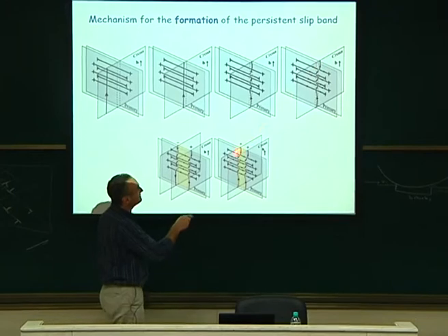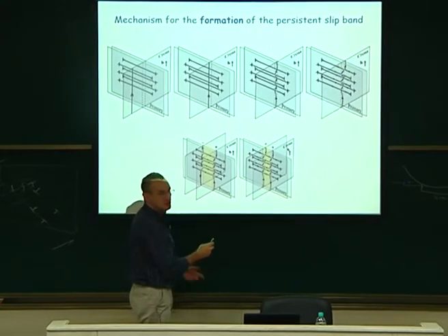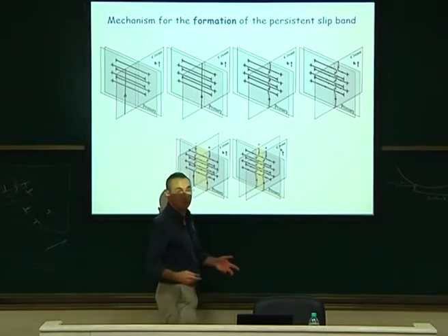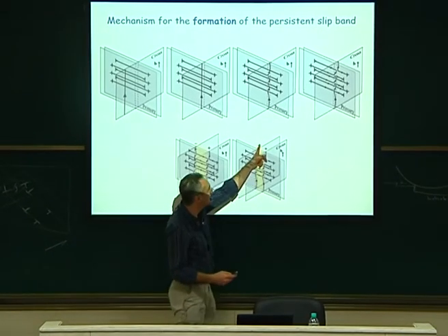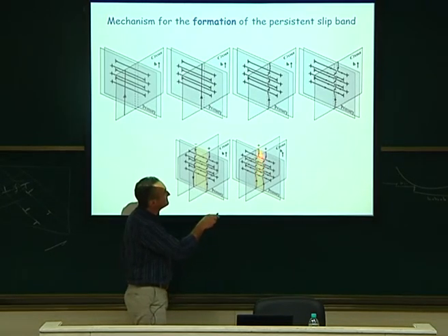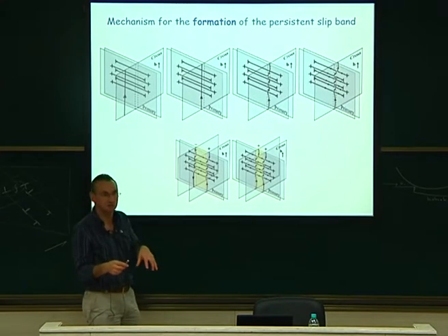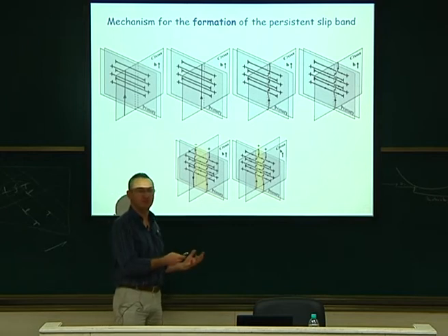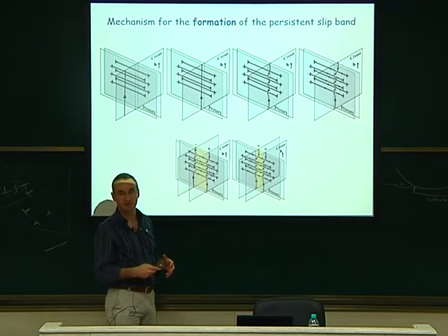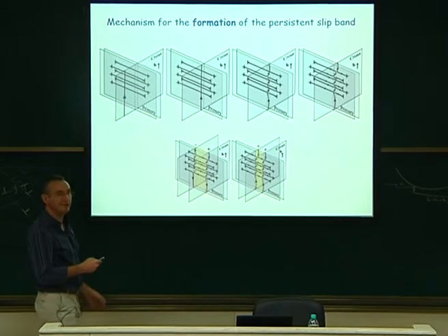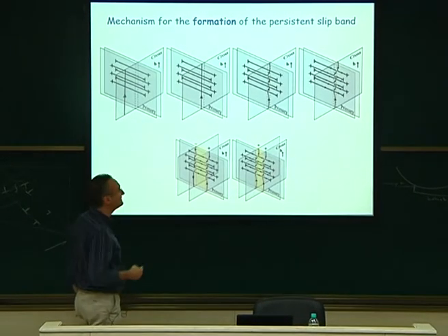If it is the same sign dislocation which is coming, it creates half prismatic loops, which is a helical turn. You have some helical turn, but the behavior is more or less similar. It means that this can still glide in that direction. In the vicinity of this channel, those dislocations are highly pinned. They cannot move. They are hard to move. They are not sessile, but I think you could say that those are statistically stored dislocations. They cannot move. They are dead, more or less. Okay. This is what we call entangled dislocations. They are totally entangled.